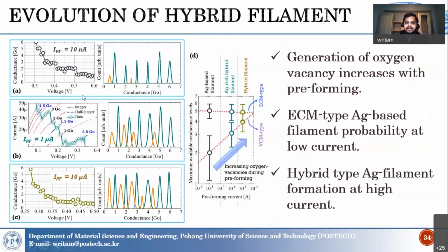But then when we increase the preforming current level, the half integer values actually start to increase. And when we have like 10 or more microampere range, it is like full of mixed integer values. So basically it can change the complete switching process of the devices with the presence of the vacancies.